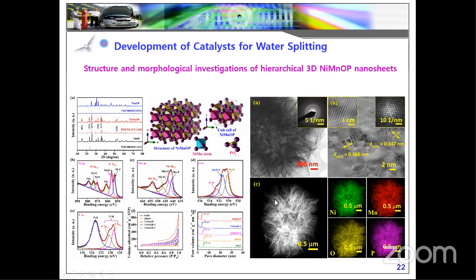And further, this study is confirmed by STEM analysis. This high-contrast image shows the material is ultrathin and highly flexible, and the material's elemental presence is confirmed by STEM EDS analysis. From the STEM EDS mapping analysis, you can see nickel, manganese, oxygen, and phosphorus are homogeneously distributed on the ultrathin nanosheet architectures.